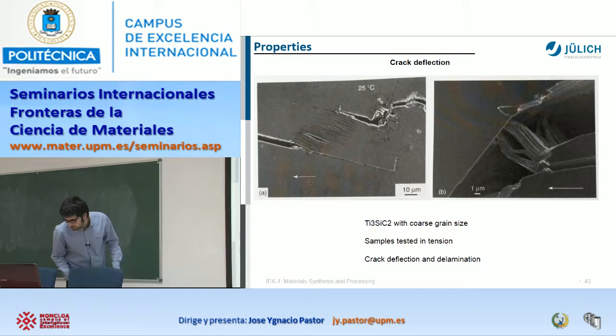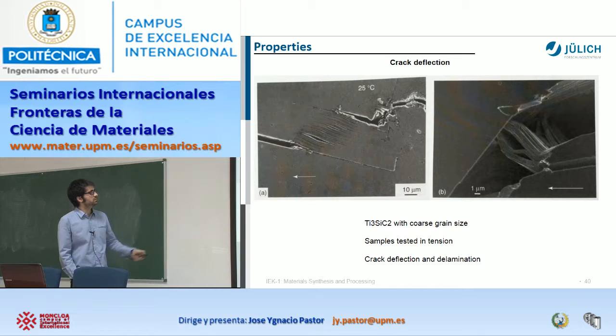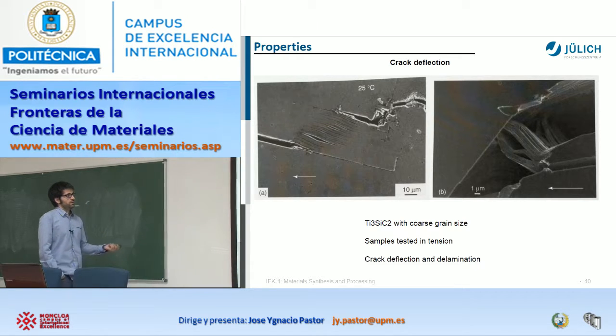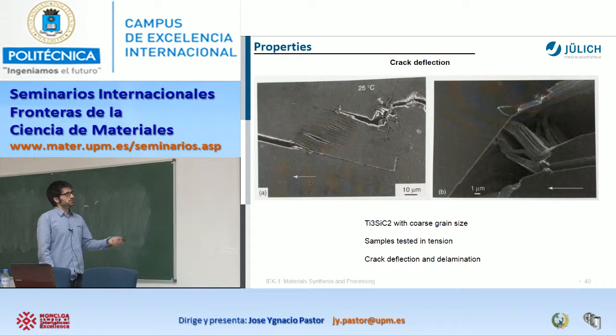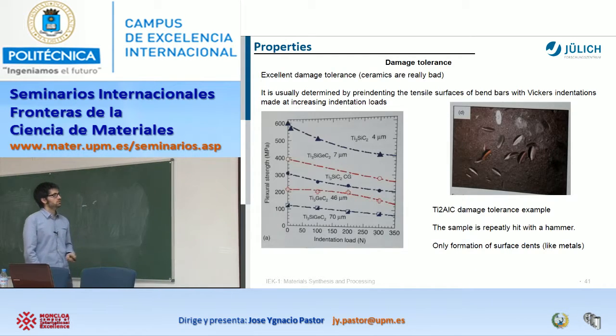Fortunately, the resolution is not as good as here, but you see here there's delamination, or here these kink bands that are moving, and of course this one is totally impossible to see in ceramic materials. That's the reason why, if the crack is deflected and delaminates the matrix, of course you absorb a lot of energy, okay? But well, anyway, this is room temperature. We'll see now at high temperature, okay?